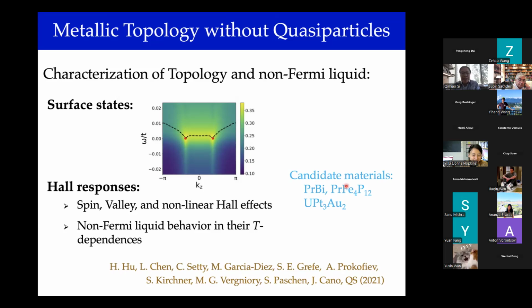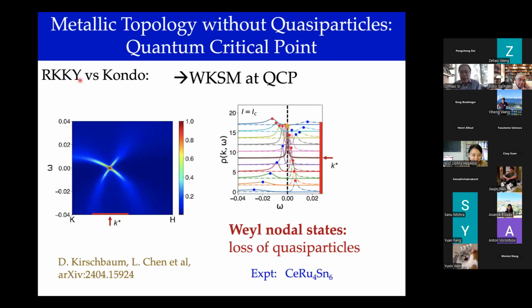This is in some sense from where I started. It's a detour, but one could ask the question, going back to the one-channel Kondo effect in this interesting lattice: could we also tune the system to the quantum critical point? And so we studied the RKKY versus Kondo interplay in this one-channel Kondo problem, reaching the quantum critical point, which is signified by h bar omega over kB T scaling, for example, in the spin dynamics. This was also in part motivated by this material, in which the neutron scattering measurements of Collin Broholm a few years ago, on samples made by Silke Paschen's group, actually show that this semi-metal system has dynamical scaling in a form that's quite similar to what's observed in cerium copper 6 gold.